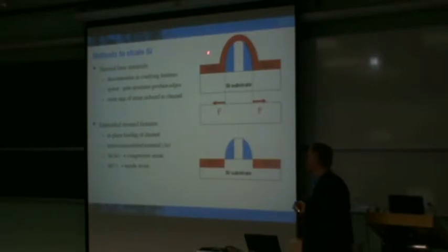Okay, so I showed the first examples of how this was implemented, and since then the industry has developed some ways, but I think we could break it down into some straightforward ways of describing what ways have been developed. And one of them is in the incorporation of stress liner materials. And that simply refers to a material that is deposited over the structure that has a residual stress within it. And this residual stress can clearly induce a change. It's really, again, due to the edge effects, due to the fact that at this region where we have a spacer that insulates the gate region from the source and drain regions, this change in geometry represents a stress concentration. And so you can think of that as a way of concentrating a force at the top of the silicon substrate here, right near the edges of the channel.